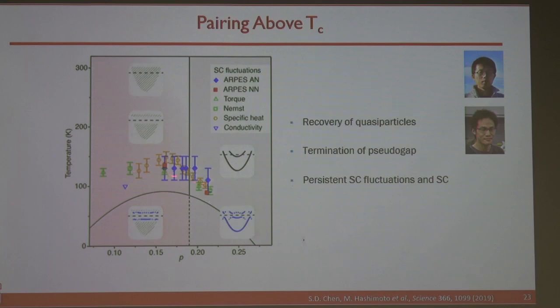Therefore, we can say that in the phase diagram, there is an energy gap across the entire doping range, which is somewhere around 30, 40, 50% above TC. And in the overdoped regime, we've tested very carefully, and it's particle-hole symmetric. And this gap is what I call the preformed pair. Okay. Then in the underdoped regime, there is a higher energy scale gap, and this is a gap I would call a soft pseudogap, and by virtue of its energy scale, we think that's related to the instability coming from the fact that it's a doped magnetic insulator at that scale. Okay.